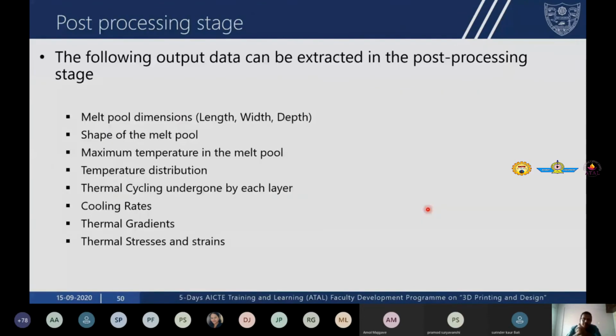Once you finish the solution, the next is the post-processing stage, where you can extract a wide variety of information from the finite element models. One piece of information that can be obtained is the dimensions of the melt pool. You can find out the length, width, and depth. As I said, a consistent melt pool is required for consistency in the build conditions. We can find out about the shape of the melt pool, which is influenced by the convective flows within the melt pool. We can find out the maximum temperature. We can find out the distribution of temperature.